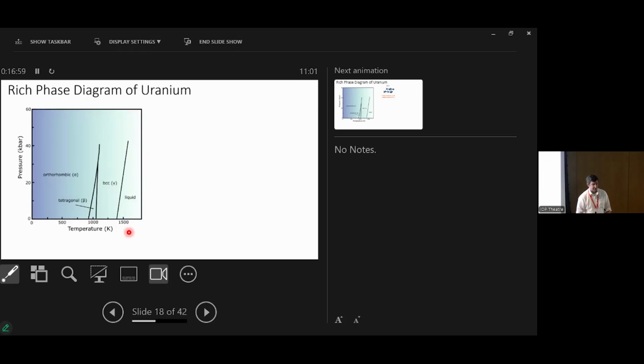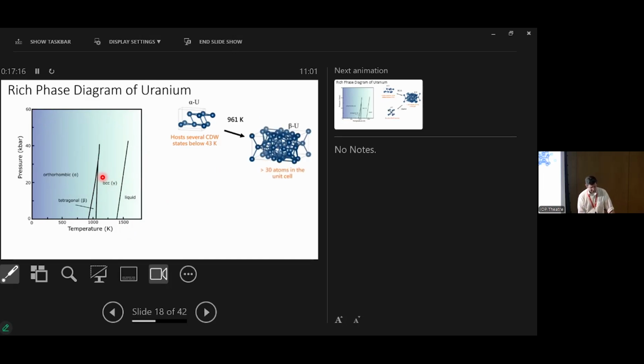Slight problem is that on the structural phase diagram of uranium, despite it being a bit complicated and interesting, there's no hexagonal close packed phase. It doesn't exist in nature. So there's an orthorhombic phase, that's the one I just talked about, which is maybe a superconductor. There's a tetragonal beta phase, which is hideous, so let's not talk about that because it's very complicated. There's a gamma phase, a BCC phase, and then many years ago, 30 years ago, there was a prediction that actually the BCC phase would relax to the orthorhombic state via a hexagonal intermediary.